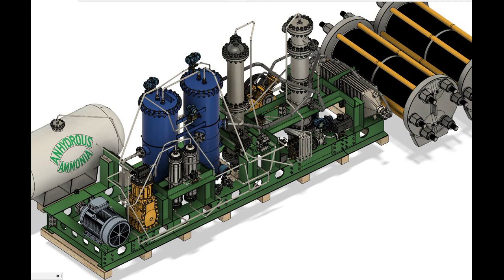For example, a 40 kg per hour ammonia plant would use only 6.9 liters of catalyst at a high space velocity of 40,000 per hour. What can be concluded from this inquisition into the downscaling of ammonia synthesis technology is that reaction kinetics remain unaffected, while increased thermal transfer does not impose major design considerations, other than minor reactor insulation. What is highlighted is that it is not kinetics, but rather compression and economic factors, that remain the obstacle and explain the preference to build ever larger plants.